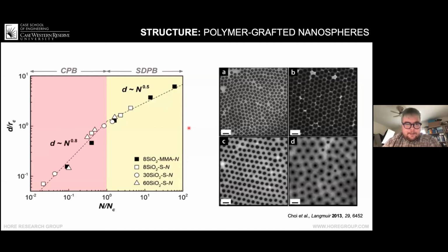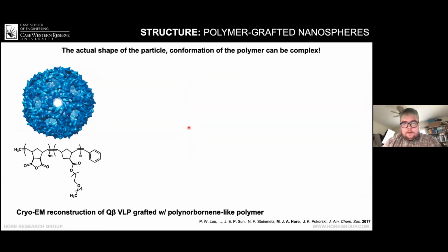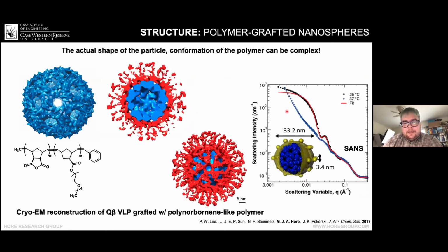One thing that you may miss if you do light scattering is the ability to simultaneously resolve different parts of the brush. So although you're seeing trends in how the thickness of the brush is increasing, you may not be able to see, for example, that the inner region is a spherical shell and that there are globules on the outside. You may only see from light scattering that the thickness of the shell increases, let's say linearly, and then afterwards increases as some different power, but it doesn't necessarily tell you the shape and the even distribution of these on the particles. So the neutron scattering is giving you